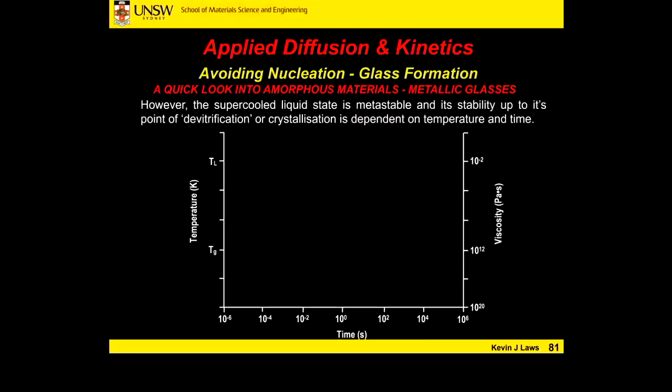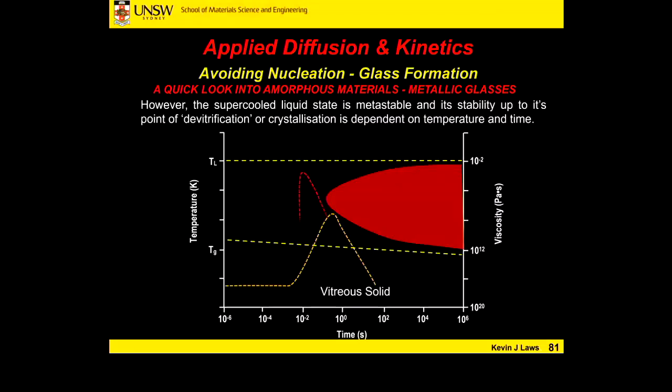We also had a look at processing of these materials and how this is also a nucleation and growth defined step. Basically, if we have a vitreous material, a PET plastic bottle, a silicate or modified silicate glass, we only have a specific amount of time in which we can heat our material above our glass transition temperature, do our forming activities and cool it down before this material crystallizes and its properties change. So utilisation of the amorphous structure in the supercooled liquid state for forming processes is commonly used by industry today, like the plastic bottle that you're drinking out of, and everything else.